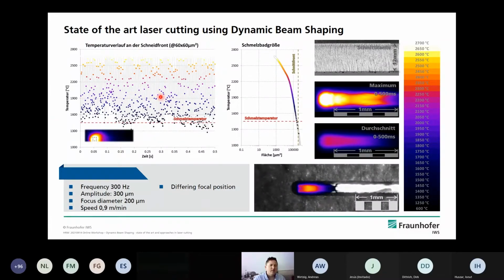What we can see in the diagram and also in this small image or video below is a pulsing of the surface temperature of the cutting front. So we can see that by distributing the energy, we also influenced the surface temperature. And as you remember from my first slide, the energy or temperature distribution has an influence on the material transport. And even the cut quality is quite a bit better compared to the beginning. So on these two slides, we can see there is a quite large impact if we use dynamic beam shaping, and we could increase the quality.